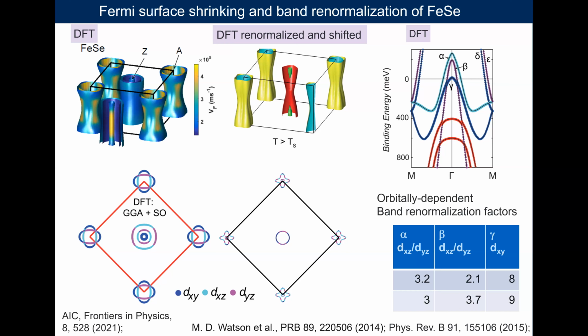So when you compare ARPES and DFT, then you can look at the different band renormalization. And as I mentioned before, in iron chalcogenides in particular, if you look at the XZ and YZ bands, they have a factor of about 3 to 4. Whereas if you look at the dxy band, which I'll show you in a minute, this renormalization factor is 8 to 9. So we have these very unusual orbitally dependent renormalization effects.